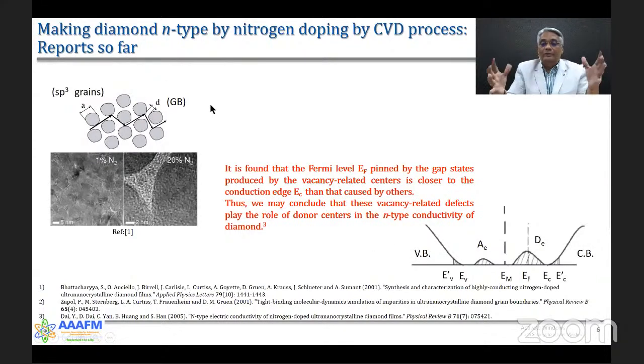When you start with nanocrystalline and ultra nanocrystalline diamond and implant it, most of the implanted ions tend to diffuse towards the grain boundaries, and with further annealing, they in turn diffuse into the grain. So unless you have the carbon atom being replaced by nitrogen and phosphorus, leading to an electron being donated to the lattice, you will not see conductivity enhancement.